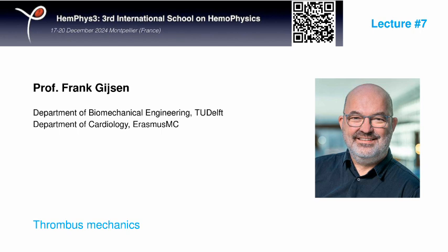Let me start by saying that, of course, during the whole procedure, the thrombus is subjected to a very complex 3D loading environment containing all the mechanical loading components that you can think of: tensile, shear, compression. So all of them are individually relevant. Using these simple experiments gives us the opportunity at least to compare part of that mechanical behavior. But to fully understand what is going on in that thrombus, you need all of them, obviously.